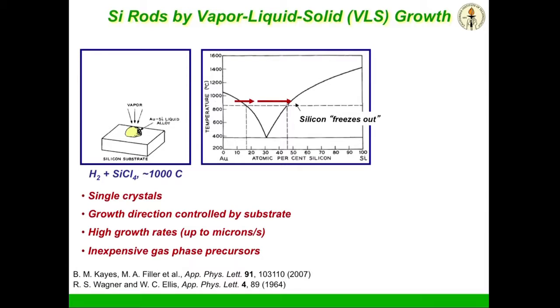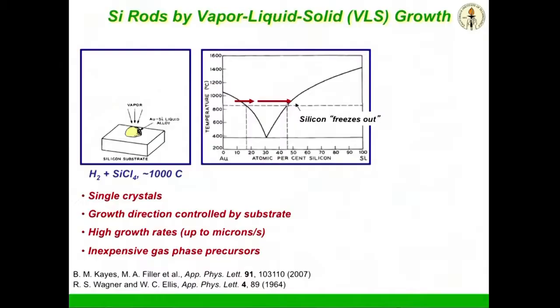The way we do this is with the so-called vapor liquid solid growth approach, where you take a silicon vapor precursor like silicon tetrachloride, and over a growth catalyst, there are 3 suitable growth catalysts, according to the phase diagrams, gold, copper, and nickel, that will crack that silicon and make a molten silicon gold alloy. And as you feed it more silicon precursor, in our case at atmospheric pressure, so in something like a toaster oven, literally, then you dissolve more and more silicon until it reaches its solubility limit.